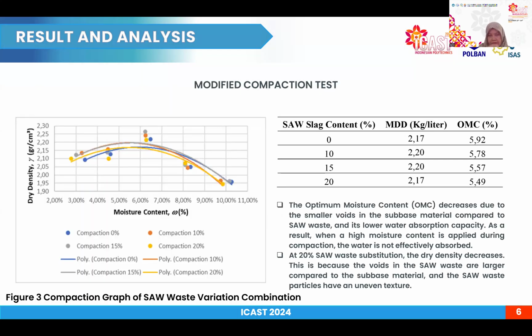This is the result of the modified compaction test. This test aimed to determine the maximum dry density and optimum moisture content, or OMC. The OMC served as a benchmark for adding water when preparing the CBR test sample. As we can see in figure 3, the optimum moisture content decreases due to the smaller voids in the sub-base material compared to SAW slag, and its lower water absorption capacity. As a result, when a high moisture content is applied during compaction, the water is not effectively absorbed.